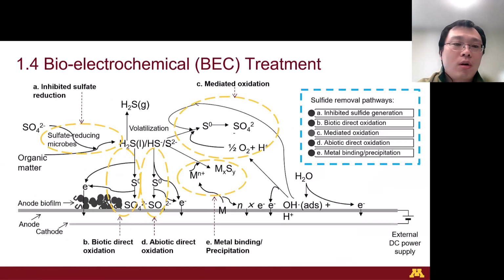So bioelectrochemical or BEC systems offer a promising alternative by leveraging microbial activity and electrochemical reactions to mitigate emissions. In our system, an applied voltage from an external power supply facilitates multiple sulfide removal pathways, mainly including, first of all, inhibiting the sulfate reduction performed by the sulfate-reducing microorganisms. Second, the biotic oxidation, sulfide oxidation by microbes inside the anode biofilm. Third, the mediated oxidation assisted by the anodic oxygen generation.